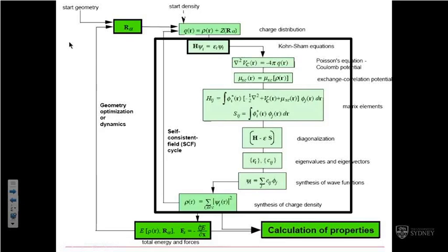then you can get the corresponding total energy and electron density. But if your atoms are not at the ground state, if they are experiencing a force, then there is another loop, like outside of this loop. If you want to relax your atoms, you can. You say, calculate the force on the atom, and if there's a force in that direction, you take a small step that way to reduce the force.